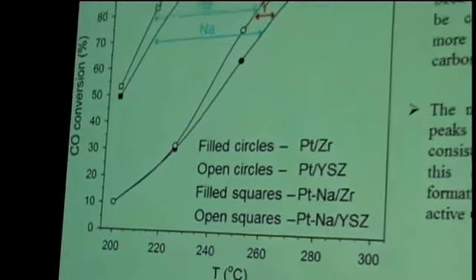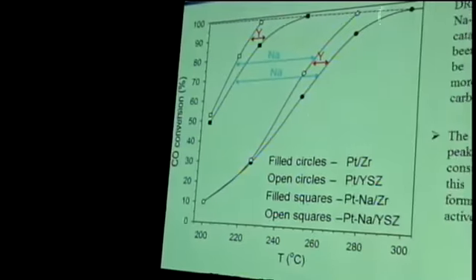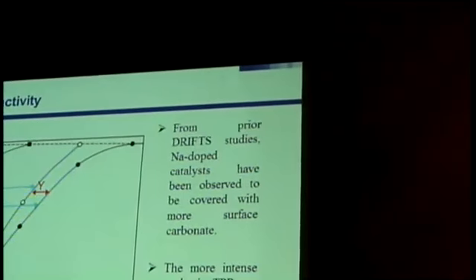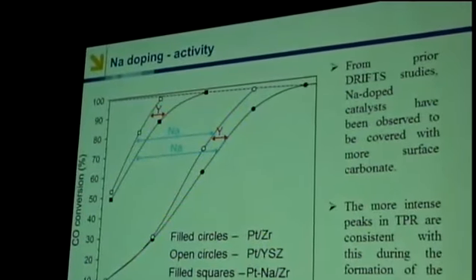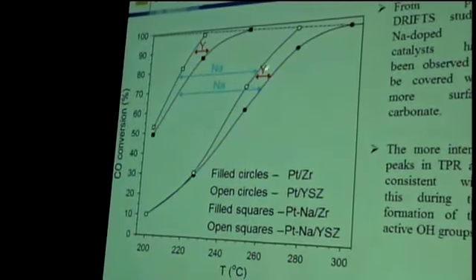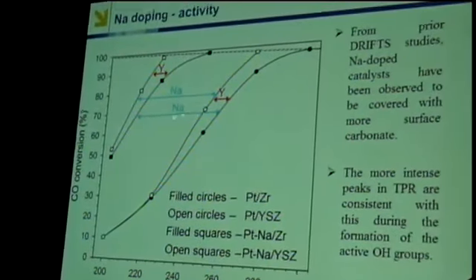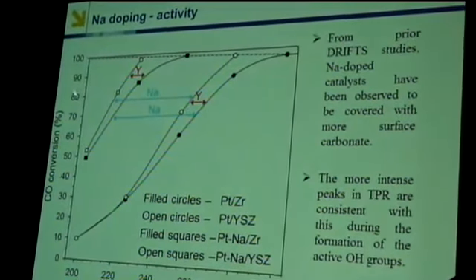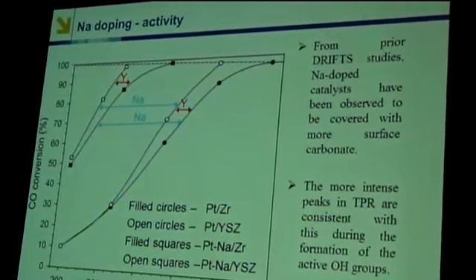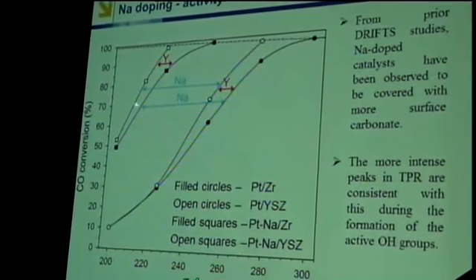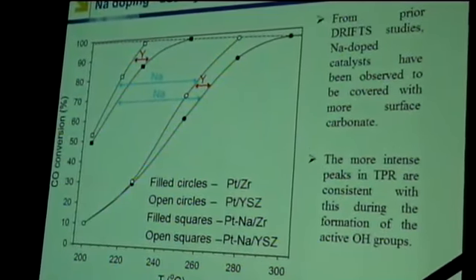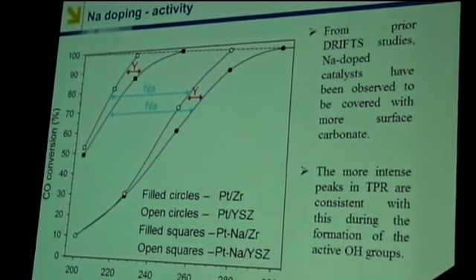Okay, so here we have the effect of sodium and yttrium doping on water gas shift rates. So here's our undoped platinum zirconia catalyst. This is the effect of yttrium. At 2% platinum levels, the effect is not as significant as we saw with the 0.5%, but nevertheless there is an effect. This is the effect of the sodium. It's really a significant change. And of course the best catalyst here has both sodium and yttrium doping. Remarkable change.